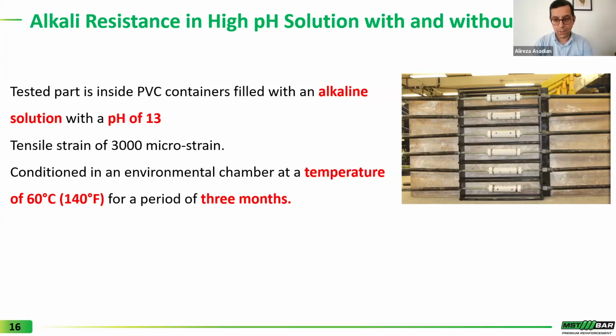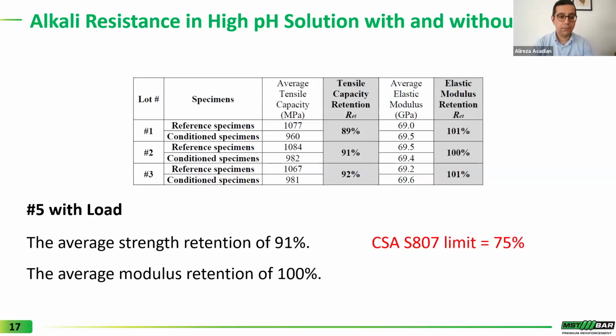then after that, the conditioned or aged rebar is tested to check the tensile strength as well as modulus of elasticity retention of the rebar. So what you see here is the table showing the alkali resistance of number 5 MST bar under load. And this test we have done at the University of Sherbrooke in Professor Brahim Benmokrane's lab. And as you can see, the average strength retention of MST bar was around 91% of ultimate tensile strength, and the average modulus retention was 100%, meaning there was no reduction in modulus of elasticity due to exposure to alkali solution. And for your reference, the limit in the CSA S807 material specification standard is 75%.